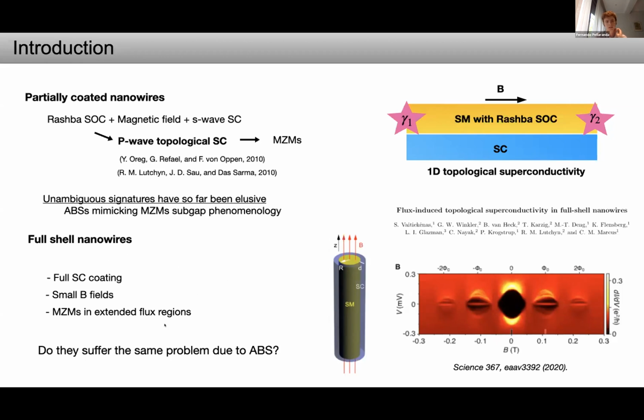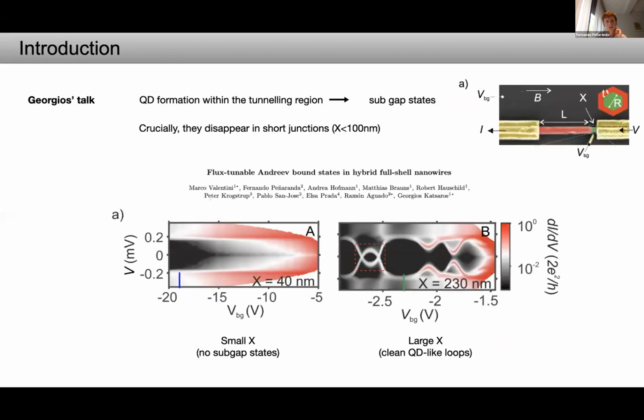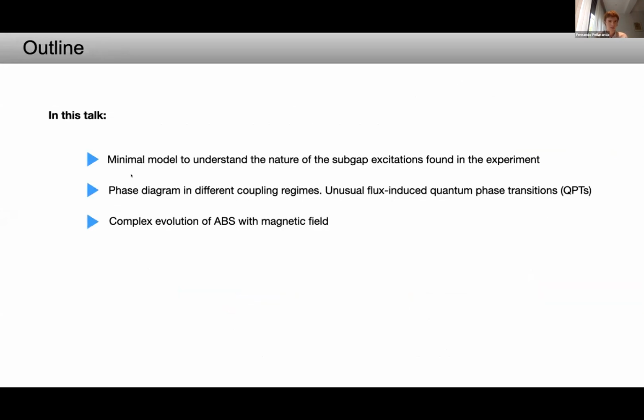So then the question arises, do they suffer the same problem due to the presence of trivial states? Well, in Jorgos' talk, we have already seen how quantum dot formation within the tunneling region could lead to subgap states, and they crucially disappear in short junctions below a typical threshold of 100 nanometers, whereas for larger regions, we can see very clean and clear signatures of quantum dot-like subgap states. So in this talk, we will introduce a minimal model that helps us to understand the nature of the subgap excitations found. We will also describe the phase diagram of the system in different coupling regimes, finding an unusual flux-induced quantum phase transition. And finally, we will also study the intriguing evolution of Andreev bound states with magnetic field.